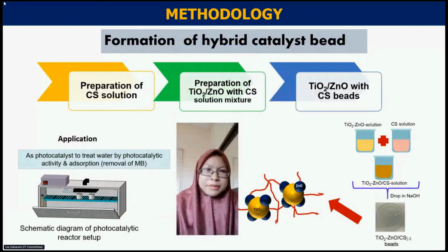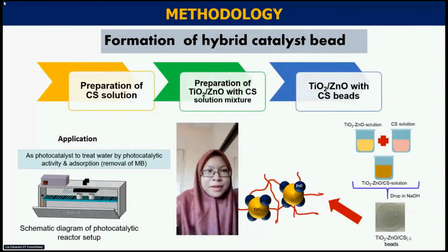The hybrid system was prepared using a simple acetate process with acetic acid as the medium. Then the obtained photocatalyst was characterized in terms of its surface and structural properties, before proceeding with the photocatalytic analysis under the visible region using methylene blue as the model of synthetic dye pollutants.